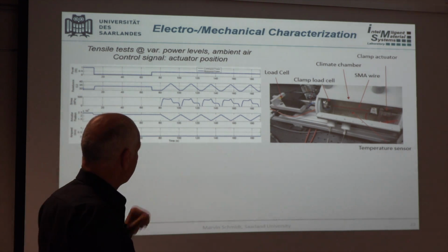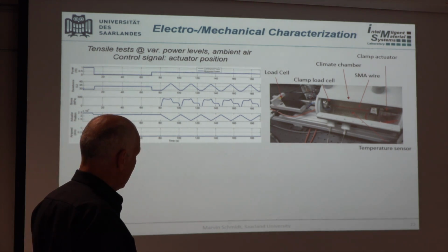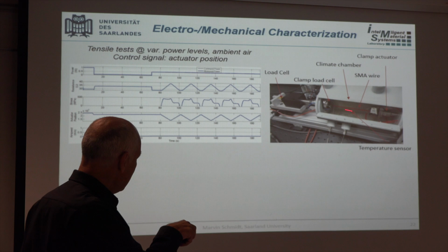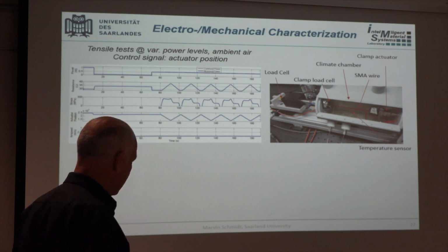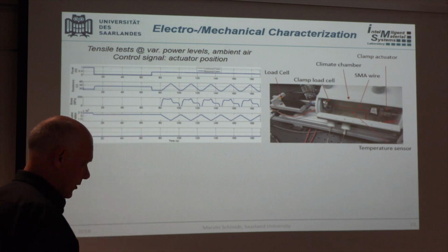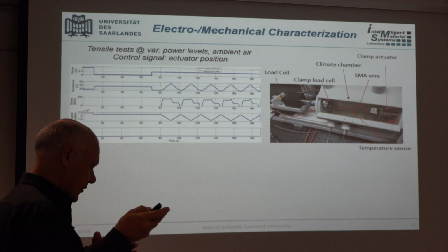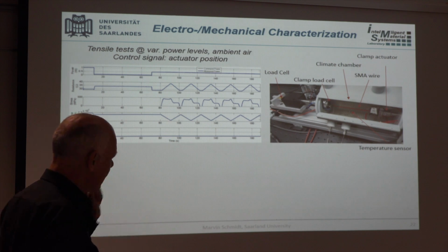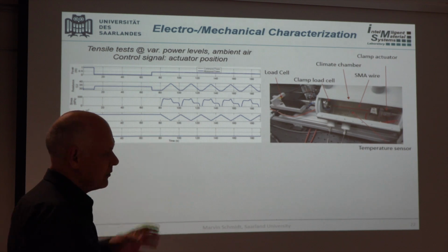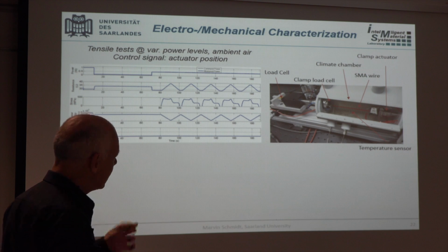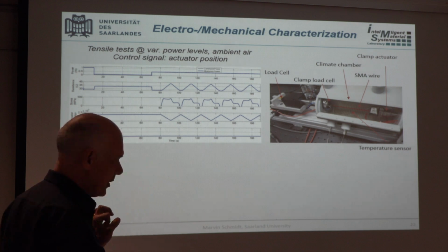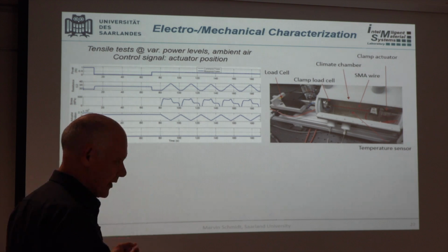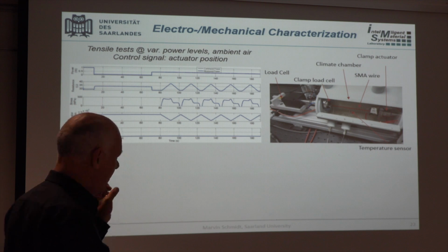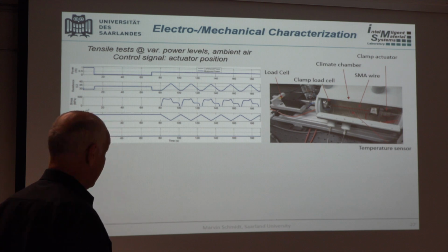So here you see an example of some measurements with those, and I'm not going to go through all the details of the measurements with you. This is a little setup that we built to measure microscale wires down to about 25 microns. The 500 microns that you saw in the movie was on the upper end of commercially available actuated wires. 25 microns, it's like a quarter of the diameter of your hair, is on the other end of the spectrum.